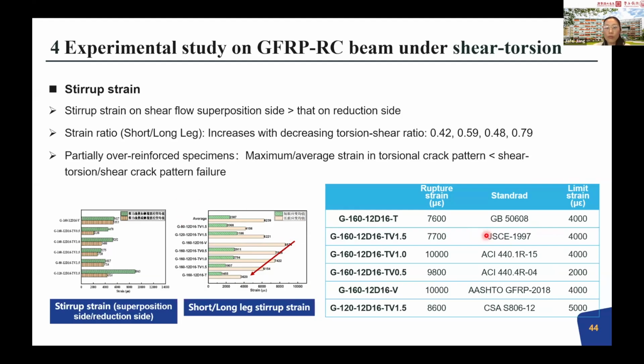And also, we're finding that this is a different type of scenario, and we found the rupture strain ranging from 7,000 to 10,000. This is the rupture strain, which is higher than the limit strain in the code for shear. But this is a static value. We haven't encountered the reliability behavior.